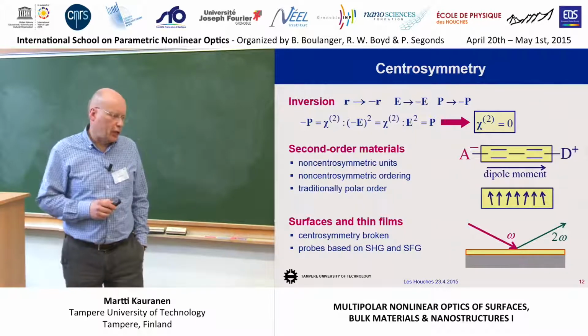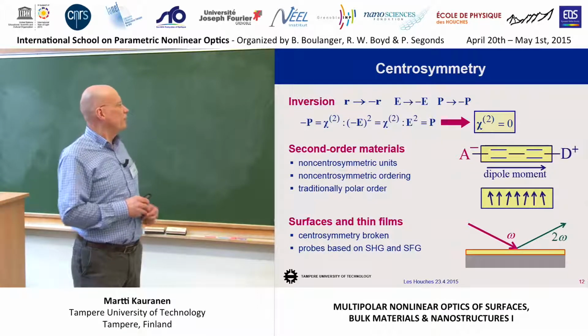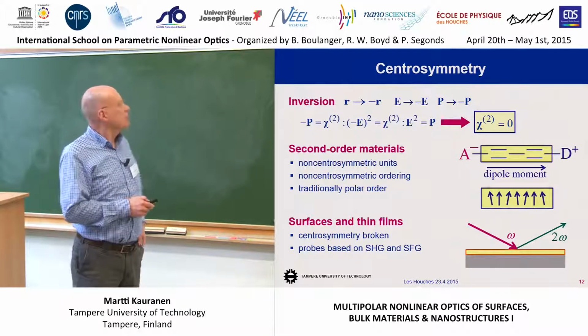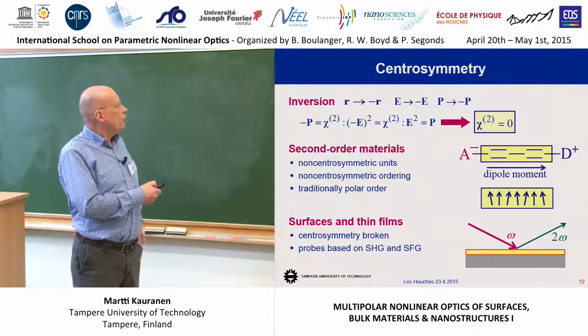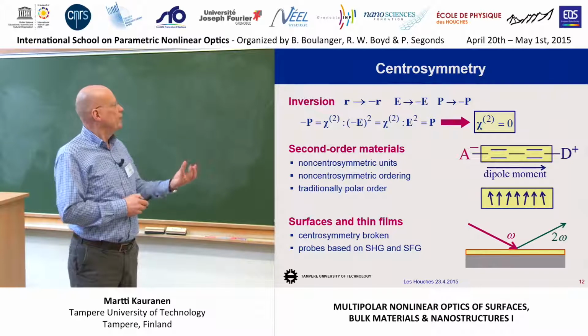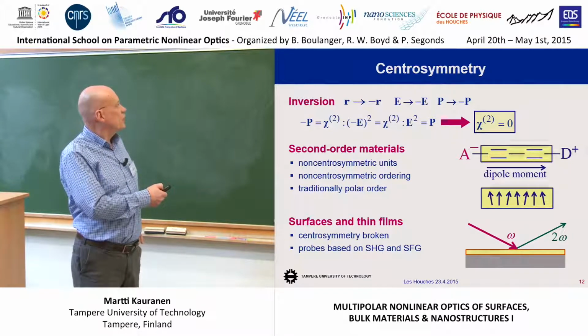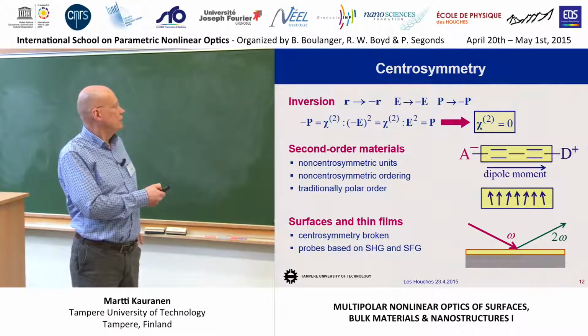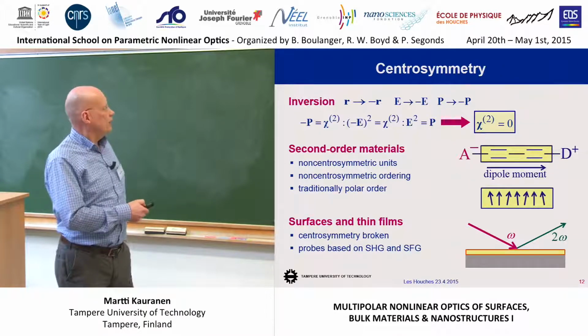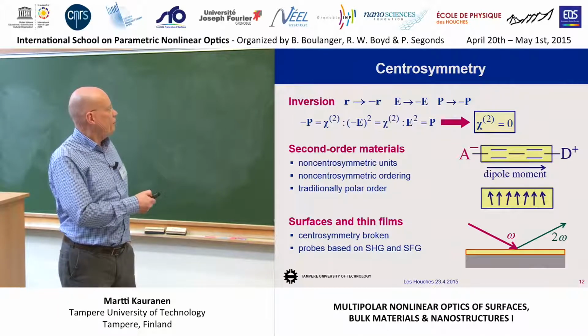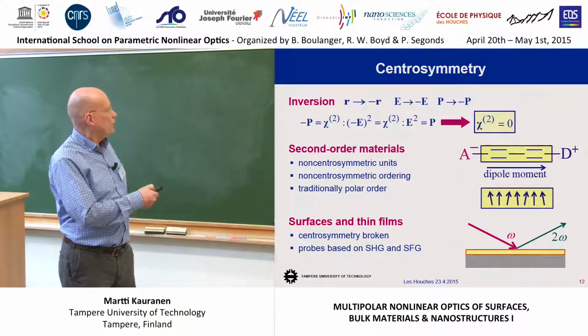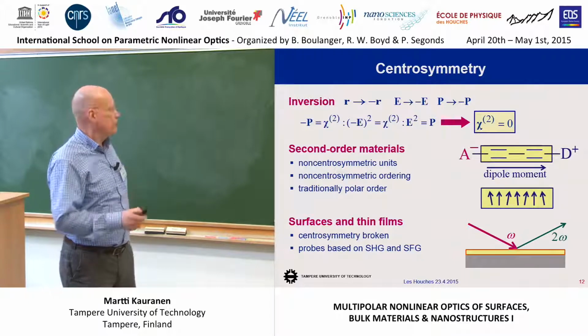And then, if you study nonlinear optics, this is probably one of the basic, most powerful rules. If your material is centrosymmetric, such that inversion operation is a symmetry operation. Inversion means that once you fix the origin in your material system, and then you change the sign of the coordinates of all the atoms, the system looks the same, and it turns out that the electric field and the polarization transform the same way as the position vector. And then if you do the calculation in the inverted coordinate system, minus P depends on minus E squared, which is E squared, which is the original definition of the polarization. You compare these two, and you find out that the vector can be its opposite only if the susceptibility vanishes. So no response.